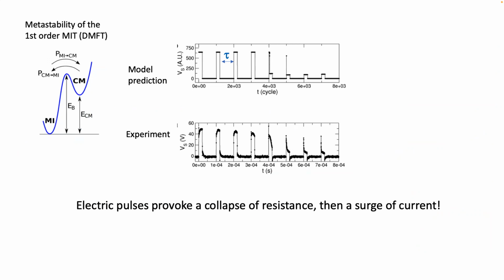So from this insight of DMFT, we imagined that if we have a Mott insulator as the stable state, somewhere in some phase diagram, a correlated metal should be in a metastable state. So by applying a strong electric field, we promote parts of the material to go from the Mott insulator to the correlated metal. But if this is metastable, there should be a barrier of stability, and this system should have an associated time to relax back to the Mott insulator.